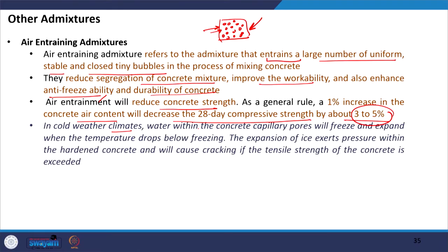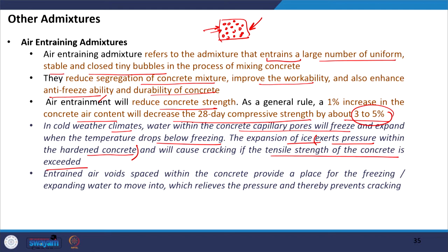In cold weather climates, water within concrete capillary pores will freeze and expand when temperature drops below the freezing point. The expansion of this ice exerts forces within the hardened concrete, leading to cracking if the tensile strength is exceeded. The entrained air void spaces provide a place for the freezing, expanding water to move into, relieving pressure and preventing cracking. This is the basic reason why air entrainment is important in cold weather construction.